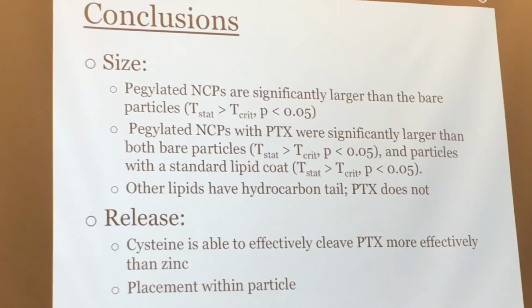After release, we found that cysteine is able to cleave paclitaxel more effectively from the particles than it is able to cleave zinc. By 100 hours, almost 50% of the paclitaxel had been released from the particle, while only 0.05% of the zinc had been released. This result is probably due to the placement of the two within the particle. The zinc is surrounded by a lipid coat, and paclitaxel is part of that lipid coat, making it easier for the cysteine to cleave the paclitaxel.